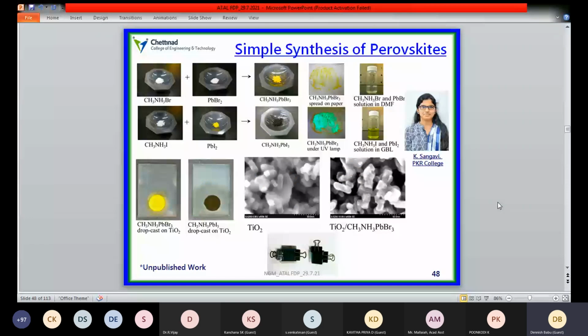We have just used methylammonium lead bromide based perovskite material. By simple mortar and grinding methodologies only, we have prepared this methylammonium lead bromide and methylammonium lead iodide based perovskites. And those two materials are dissolved in DMF and gamma butyrolactone solvent. That solution was used to fabricate this kind of devices on mesoporous titanium dioxide coated films. So these are the SEM images of the TiO2 and methylammonium lead bromide based perovskite film, and this is the device. Solar cells were fabricated with the help of those devices also.